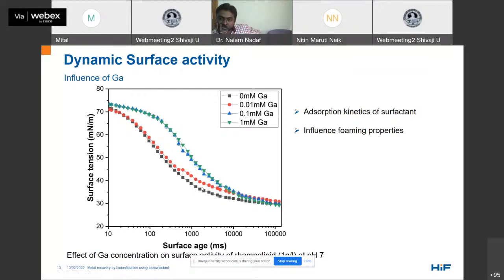Again, we can see that as the gallium concentration increases to 0.1 millimolar or 1 millimolar, there is a complete shifting of the surface activity curve of rhamnolipid towards the right. This again suggests that more rhamnolipid-gallium complexes are present in the solution now, and they take more time to reach the air-water interface.